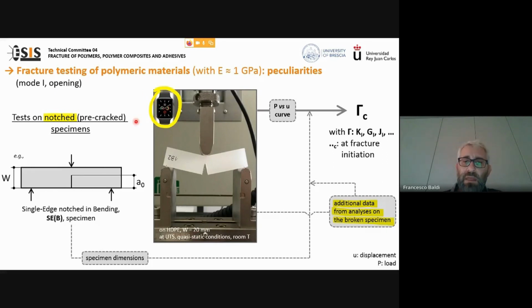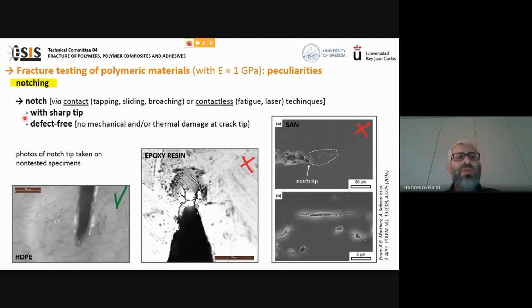From this test, I obtain the loading curves, and by using specific dimensions of the specimens and additional data determined from analysis on the broken specimen, I can determine the values of the fracture toughness parameters, K1, J1, depending on the method I'm using, at fracture initiation. So, concerning notching, in a polymer, the notch can be introduced either via contact technique or a contactless technique. The important thing is that the notch has a very sharp tip, and of course the region in front of the tip is defect-free, in the sense that no mechanical or thermal damage has occurred.